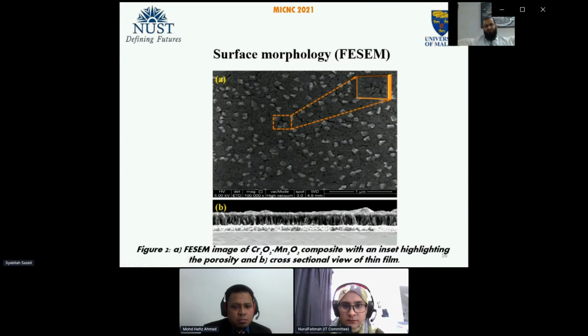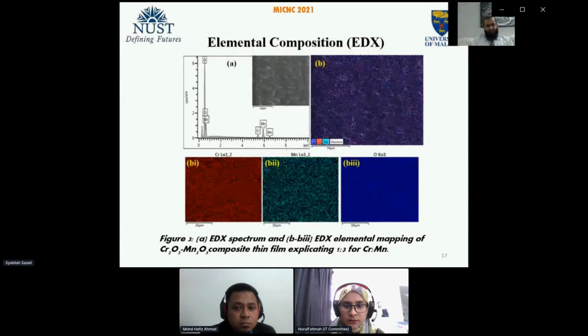The porosity is highly effective for the electrocatalytic activity, as maximum surface area is provided by the films to the electrolyte, and there is better electrolyte-electrode interaction. Further, elemental composition was performed. This elemental composition confirms that chromium and manganese are present in 1:3, and here the distribution is uniform. This mapping shows the uniform distribution of chromium and manganese, and uniform distribution confirms the better interaction between the two composite materials.